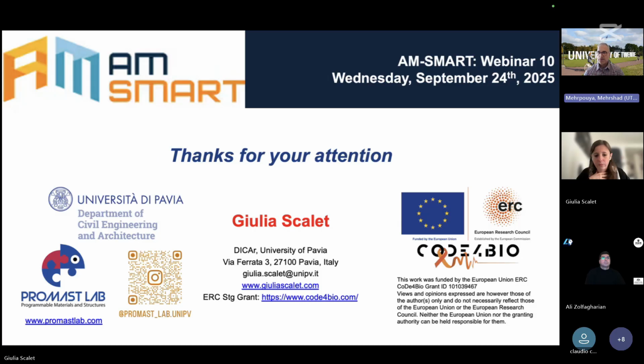Very good. The second question from Mohammed asks which of the following methods has better fixation ratio: hot programming with low programming loading time of 1 hour, or cold forming with high programming loading time of 1 day? It's a very specific question. Yeah, very specific. For the fixity, it depends on the polymer again. We work mostly on hot programming. For example, these semi-crystalline networks are really performant in terms of shape fixity and shape recovery. So the fixity depends on the macromolecular architecture, on the presence of cross-links and crystalline domains. So it depends on the polymer, not only on the programming step.